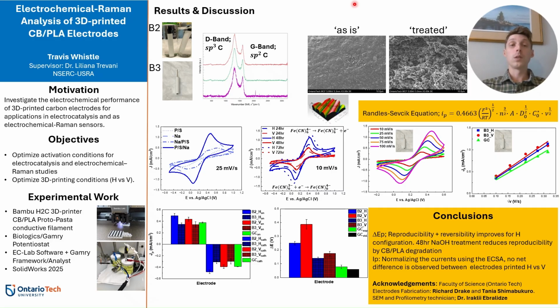Results are in good agreement to those obtained in other groups' work, confirming sodium hydroxide treatment leads to a higher amount of uncoated CB due to PLA degradation through a saponification reaction. The SEM results correspond to this. In the Randles-Sevcik analysis, all samples studied show a linear relationship between peak current and the square root of the scan rate, as expected for an electrochemical process under diffusional control.